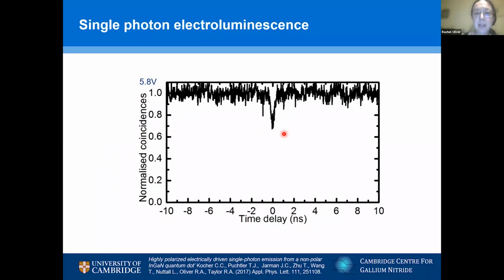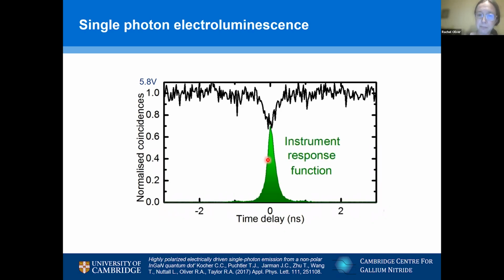Now, you're going to look at that and say, that is not a very good dip, Rachel. You said you were looking for dips down below 50% from the background level, and we haven't got that. This is a continuous wave device rather than the pulse mode I was showing you earlier. Now, the trouble with this device is that our non-polar dots with these very short lifetimes are starting to make our lives very difficult in the lab.